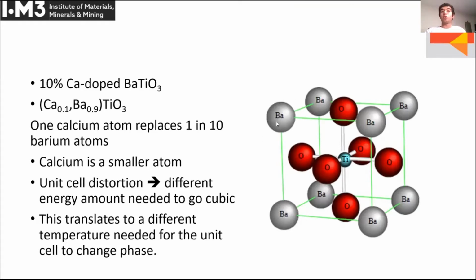Now calcium is smaller than barium, so I've put the picture here so you can imagine if we replace that corner barium atom with a smaller calcium, that would distort the unit cell a bit, and therefore the unit cell would need a different temperature to transition into cubic. That energy difference essentially manifests as that temperature difference in the Curie temperature.